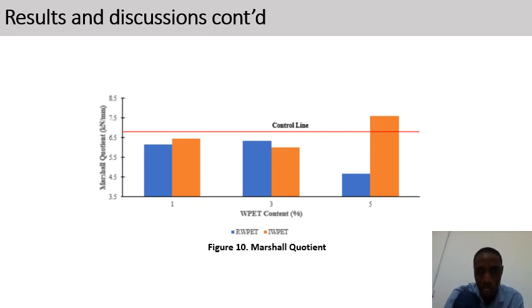The stiffness of the mixture is less than that of the control, but is higher for the irradiated PET mixture containing 5% irradiated PET content. Based on the analysis carried out, the conclusions are as follows. As you can see, the stability increases, and then due to the lack of time, I can stop here.